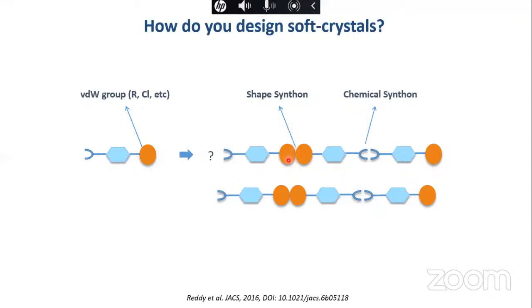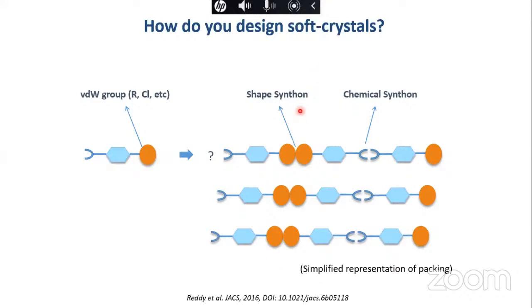Since you know that these van der Waals groups are very, very weak, if you have a plane in the crystal with completely weak interactions, then these crystals are going to be soft. If we have a dimer here, again a carboxylic acid dimer, it would be more difficult to break along this plane than when you have totally weak interactions like van der Waals groups. So if you have a crystallographic plane where you have these van der Waals groups everywhere, then that plane becomes very weak, and those crystals become softer. That means if you can make van der Waals groups pack across a plane in the crystal, you are going to get soft crystals.